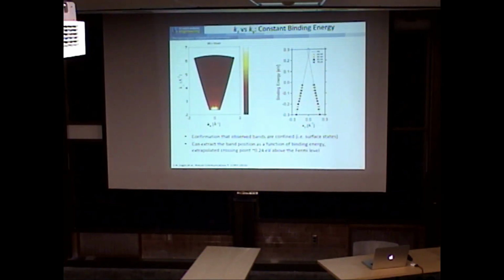So now what we wanted to do was to see if I change the binding energy. So this is a kz, perpendicular. If it's a surface state, that should be a straight line, because your reciprocal lattice of a plane is a nice straight line rather than a dot. So that tells us it's a surface state. And if I change the photon energy, the separation in plane, which is what we plotted here, will change.